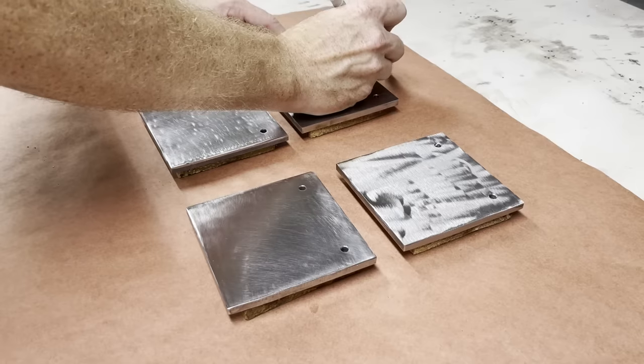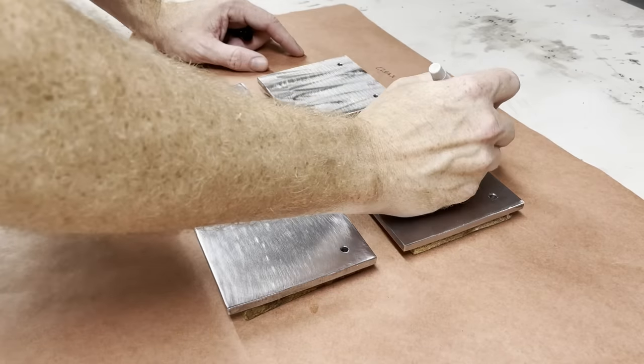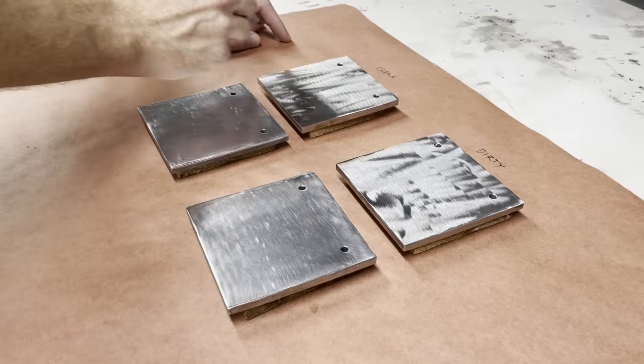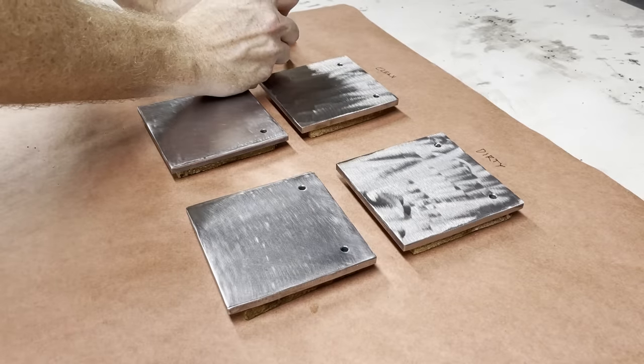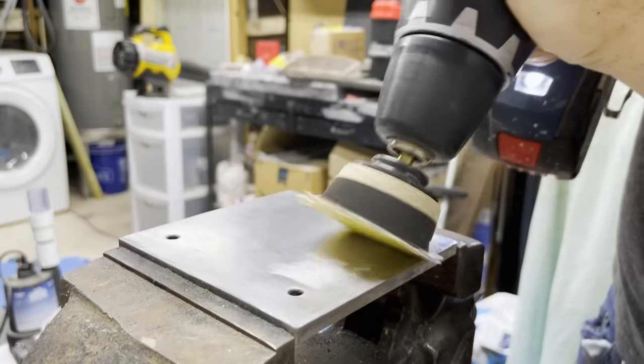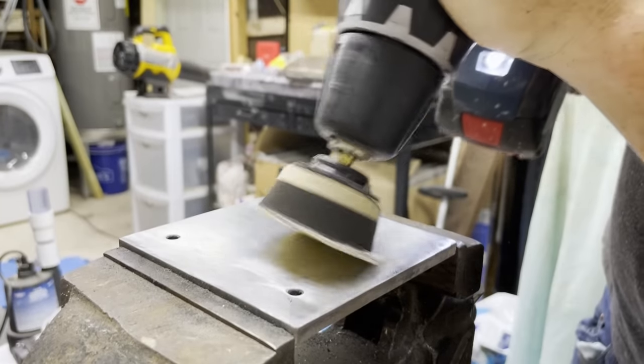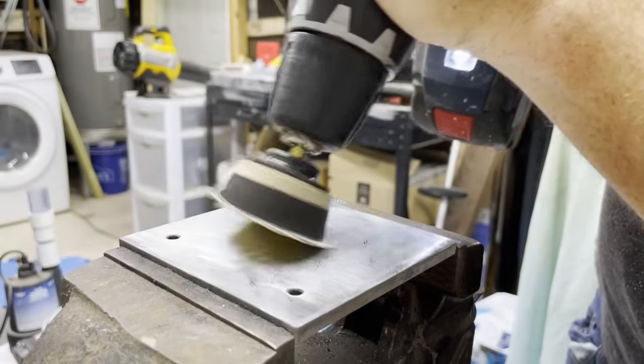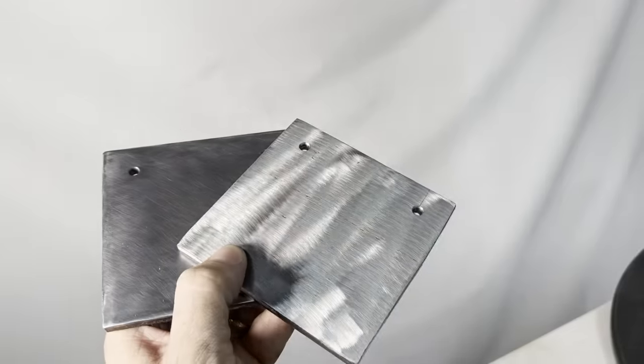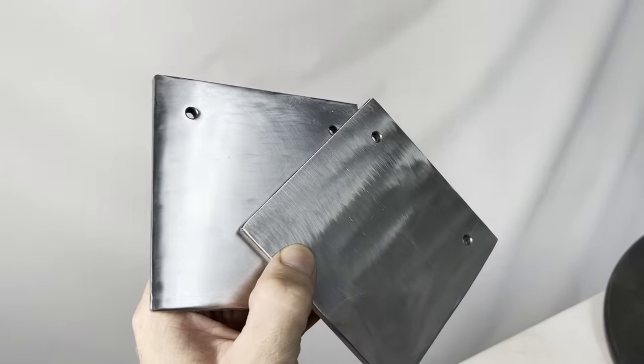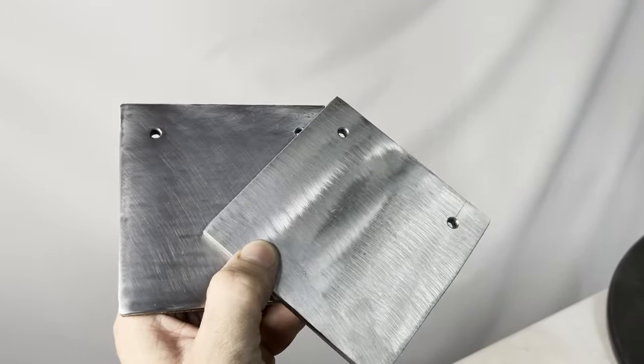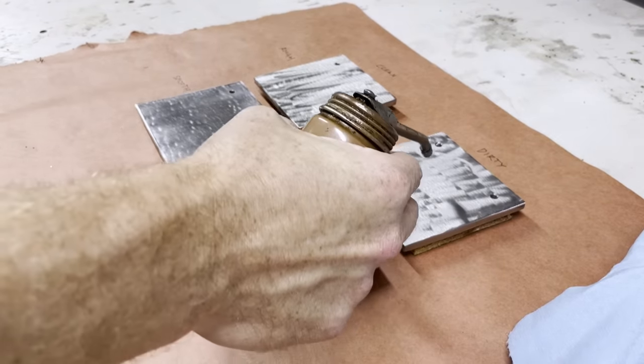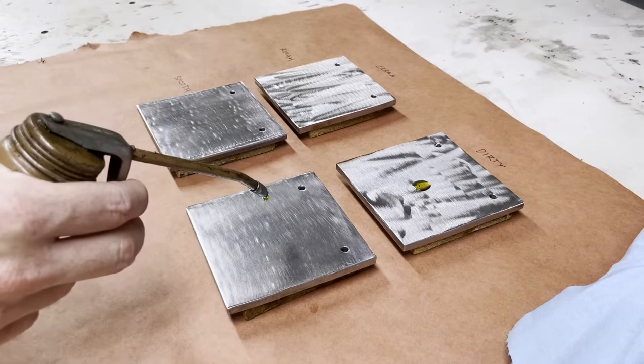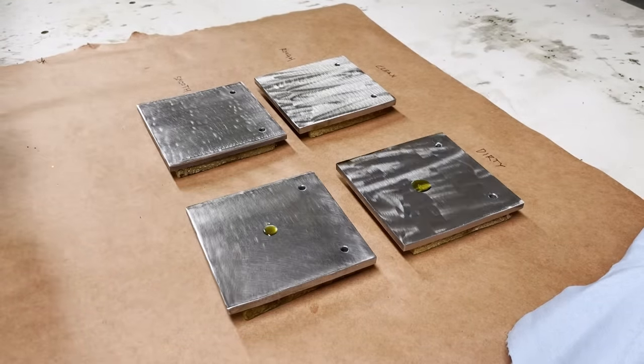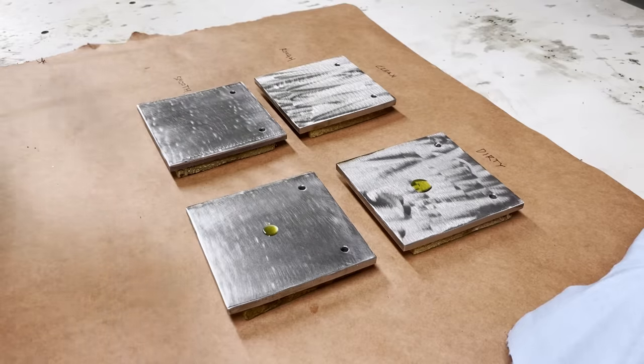Just to demonstrate the importance of surface preparation, I'm going to do a little coating of my own here in my garage. I've got four samples of steel here. Two I've roughened up using a flap disc on a grinder in lieu of sandblasting, and two I've sanded to a fairly smooth surface. They aren't mirror surfaces, but the surface profile is much lower than that of the roughened samples. I also have some oil, and I'll spread a thin coat on one of the rough samples and one of the smooth ones. I wipe the oil off with a paper towel, but no soap.